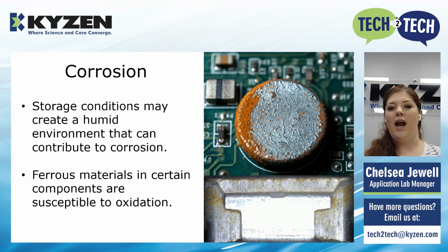So when you're looking at longer term storage or long-term shipping for these materials, if you have created a more humid environment from that board that is at an elevated temperature and there's any moisture present on it, by the time those boards have arrived where they're going, it's very common to see this type of corrosion present on anything that has ferrous qualities. Some considerations with that: what we like to say is make sure that those assemblies are back to room temperature before packaging.